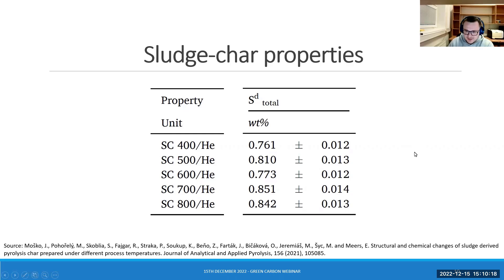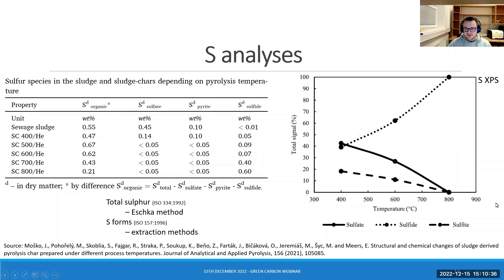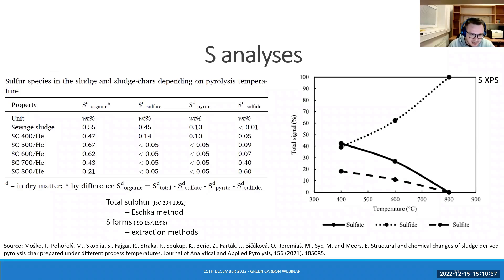So the question was: what is happening with the sulfur? We ran two types of analysis for sulfur species — the standardized ones and also X-ray photoelectron spectroscopy. From both results, we may see that the sulfate content of sludge chars decreases at the expense of an increase in sulfide content. This might be potentially beneficial because sulfides may bind heavy metals and immobilize them if present in the sludge chars.